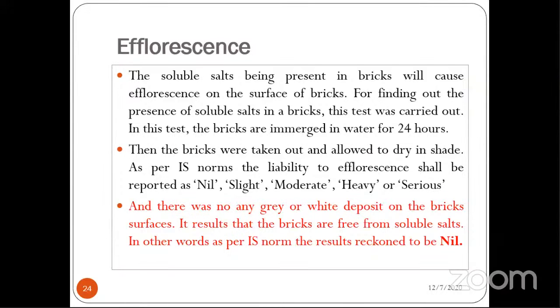The bricks are immersed in water for 24 hours. Then the bricks were taken out and allowed to dry in shade as per IS norms. And as per IS norm, the liability to efflorescence shall be reported as nil, slight, moderate, heavy, or serious. Here we get the result as nil.